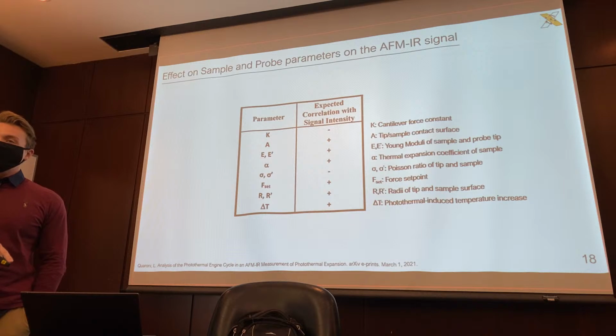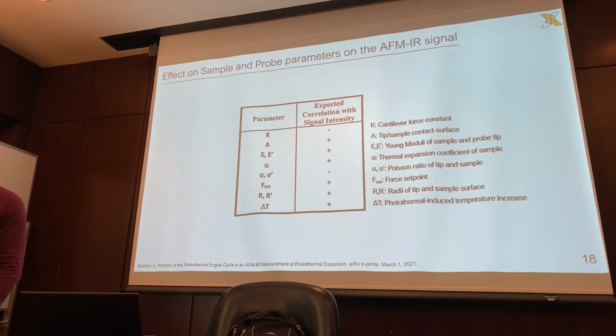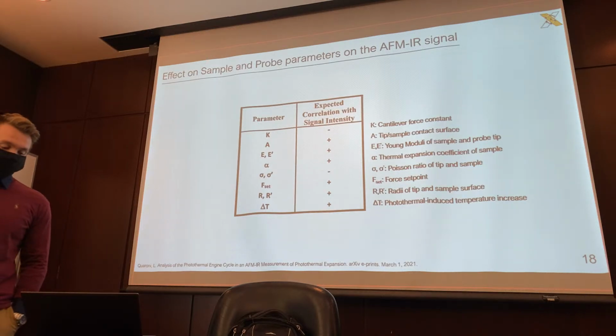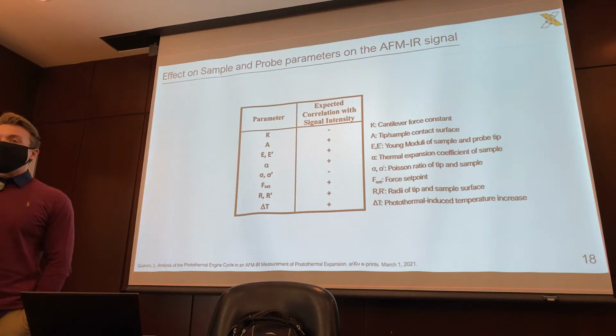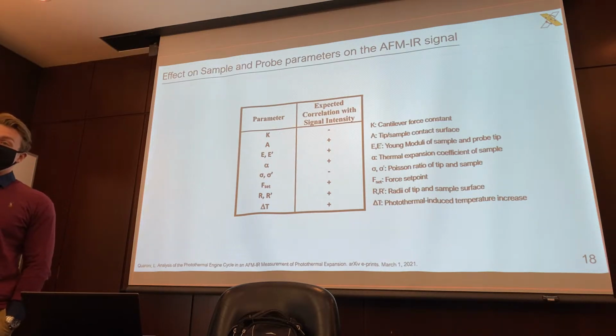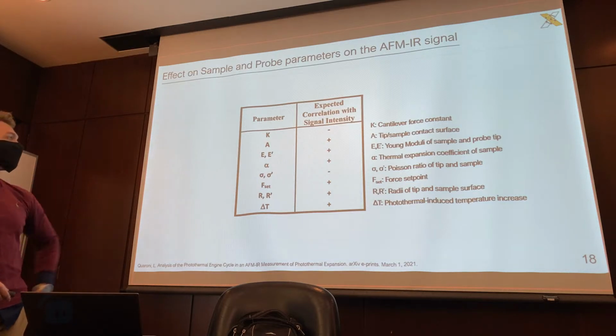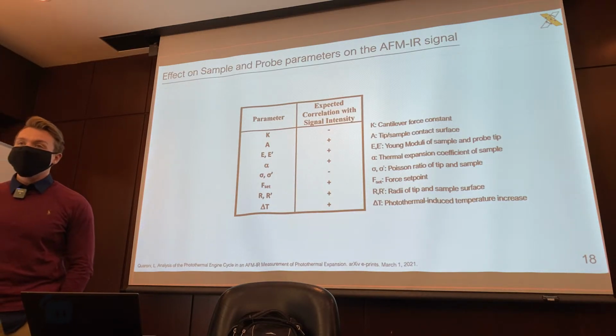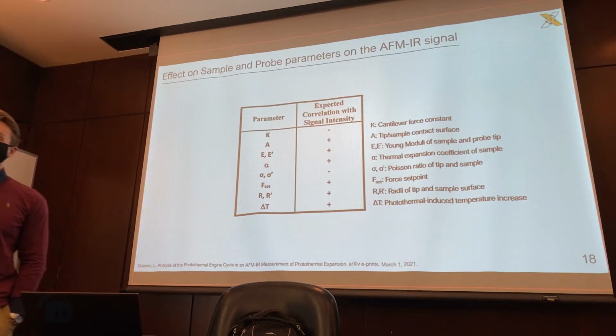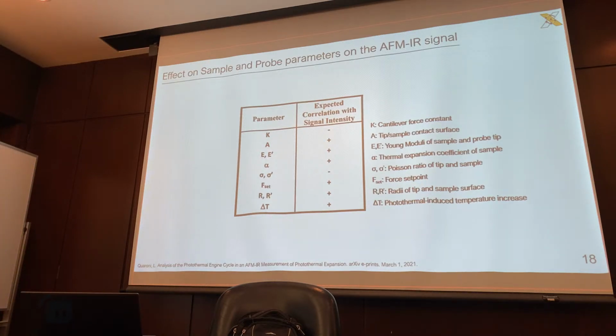So you might see, this is a little bit more controversial because Alexander Dazzi, who helped invent the technique, he believed that it increased or enhanced the AFMIR signal, the force constant or the modulus itself. There's another paper by Lahiri that debates that and says it actually decreases the signal. So in this case, they believe the school of thought that the Young's modulus increases the AFMIR signal, but it's a little bit controversial. But the Young's modulus and the force constant are indeed connected, right? Right, generally, yeah, because if you increase the modulus, traditionally, the force constant is higher.